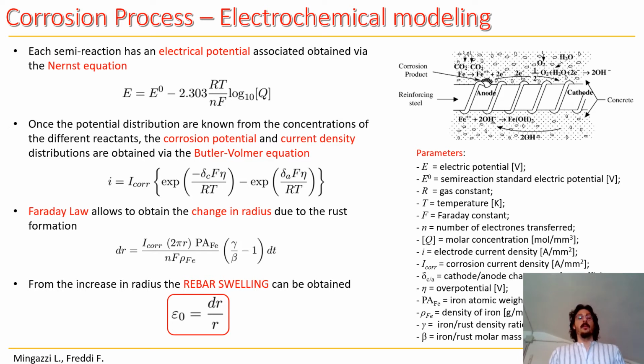And once the corrosion current density is known, it is possible to evaluate the change in radius due to the formation of the rust layer using Faraday's law. From the change in radius, we can then obtain the swelling associated with the deposits of rust by dividing the change in radius by the value of the initial radius of the rebar.